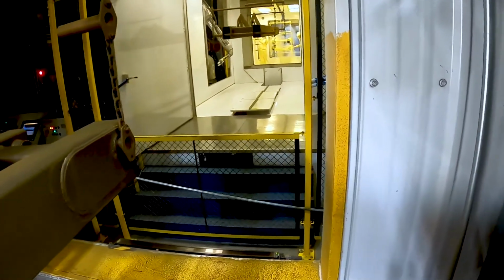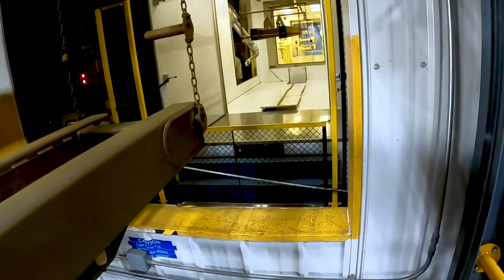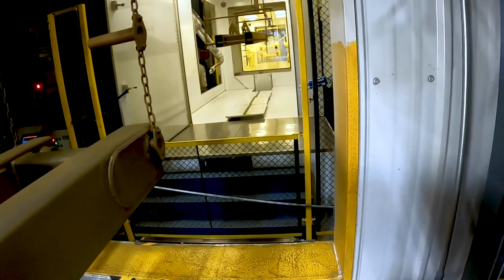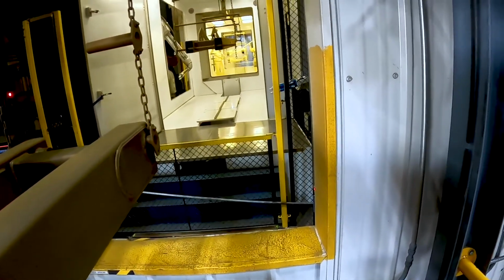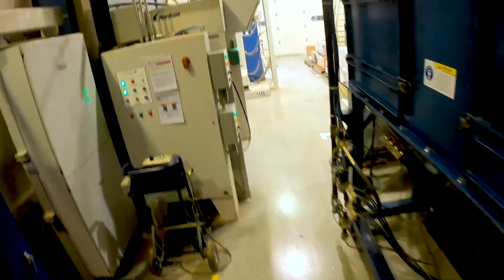That's one of the hard parts about powder coating, you're not seeing it as it would be when it's cured. You can put a paint on and look like it's covered, but if you're not thick enough with the actual powder, when you cure, it'll flow. And if it's not thick enough, it'll show right through and you'll see a light spot in bare metal, and then the whole part has to be redone. Redoing a part takes about 8 hours. Each part will then have to be burnt off, re-blasted, pre-treated, and repainted.